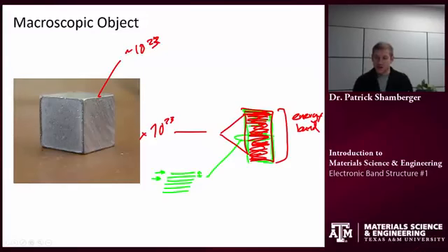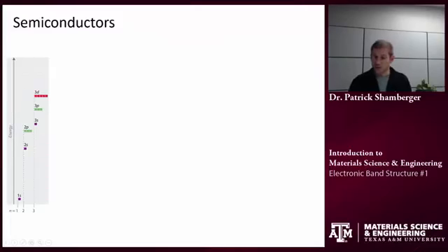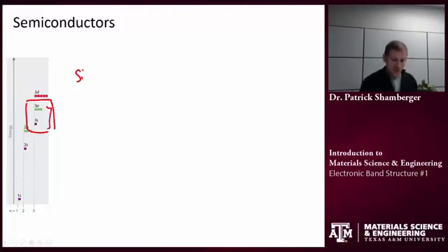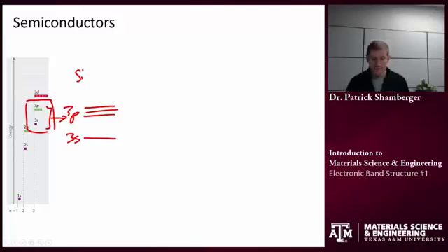That was a sodium atom. In that case, we're thinking about mixing together only these 3s orbitals, and they lead to one continuous band. It gets a little bit more complicated as we think about some of the traditional semiconductors. So something like silicon is going to have 3s and 3p electrons. And so these are both going to be valence orbitals. So when I start combining silicon atoms together, an individual atom will have 3p levels and 3s levels. Remember, there would be 3 orbitals in the p case, 1 orbital in the s case.